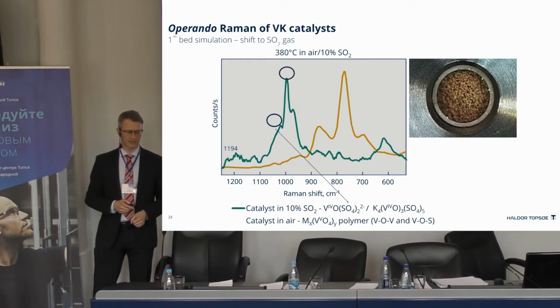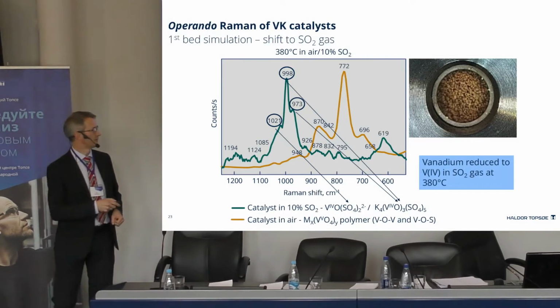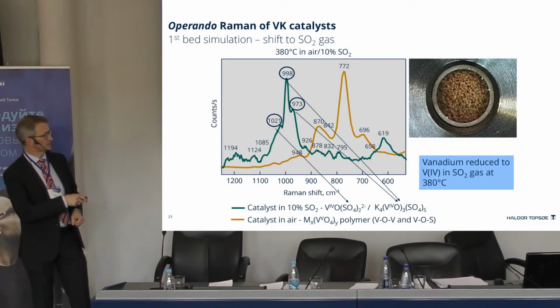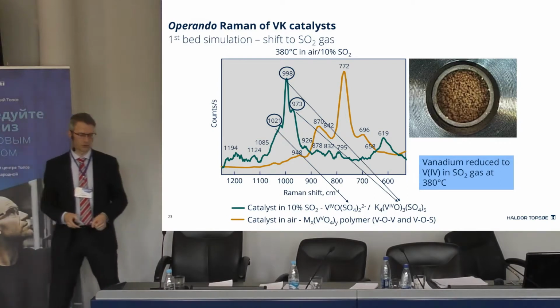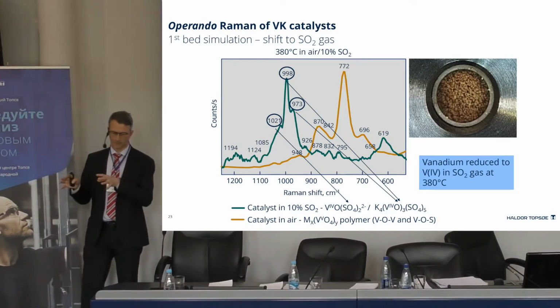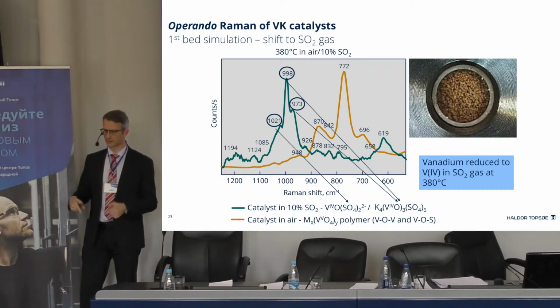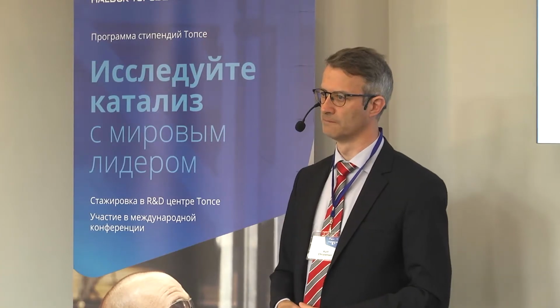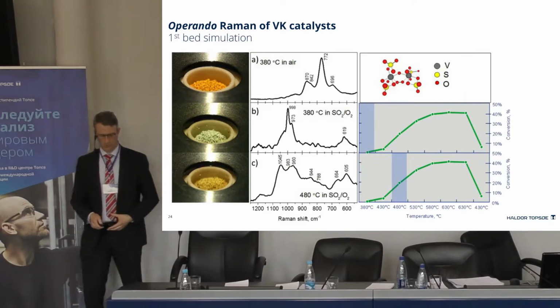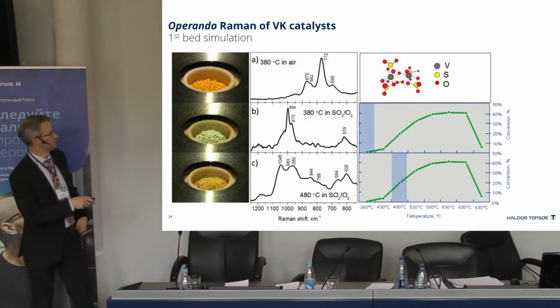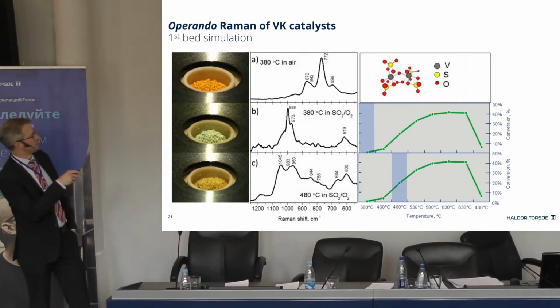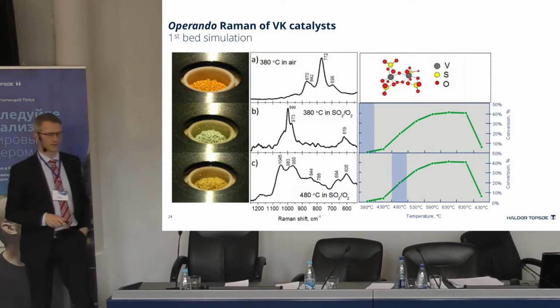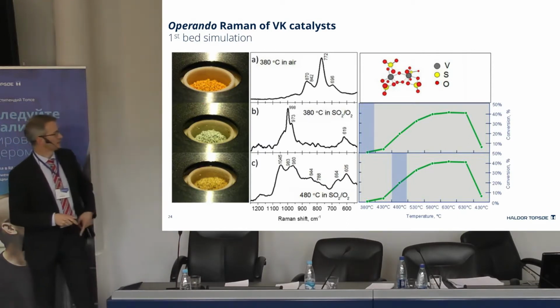These peaks can be identified to vanadium 4 species, and it clearly shows that when you introduce the process gas at 380 degrees, the catalyst, the vanadium, is reduced to vanadium 4. Here we see three steps of, you can say, the same experiment. So here we have 380 degrees in air, and we identify this dimeric vanadium oxosulfate complex in the catalyst.